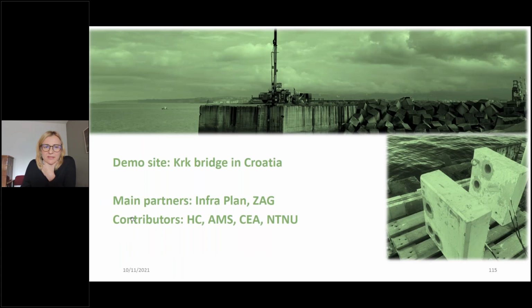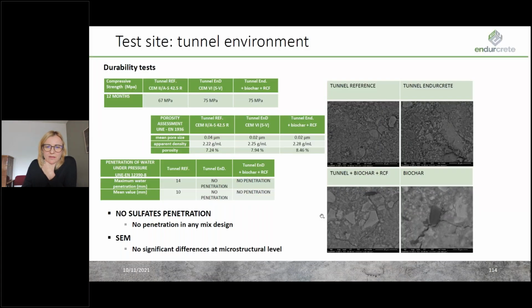Finally, for the durability tests, we can see very high compressive strength from the EnDurCrete concretes, which were produced, I didn't stress, with the CEM VI (S-V), and compared with the reference concrete produced with the CEM II/A-S 42.5 R.